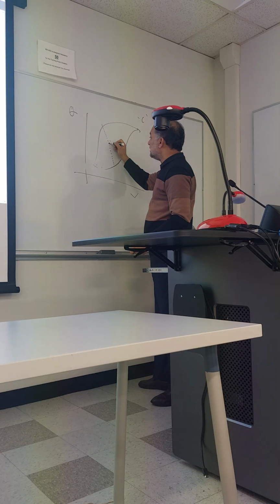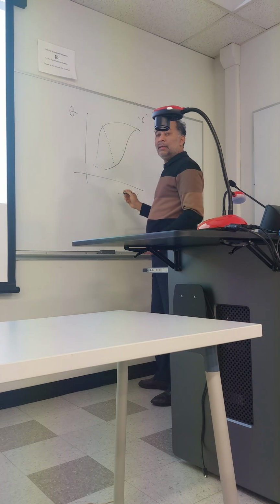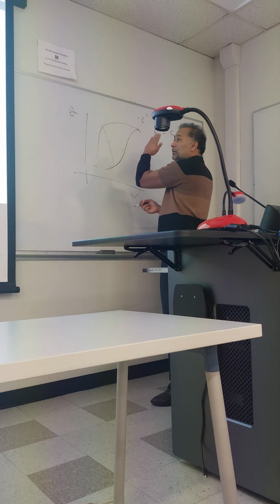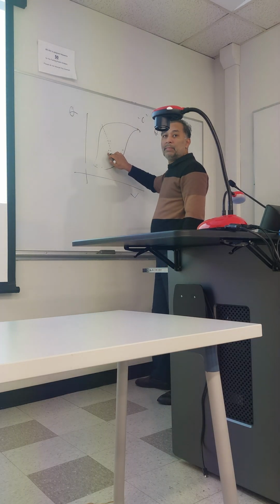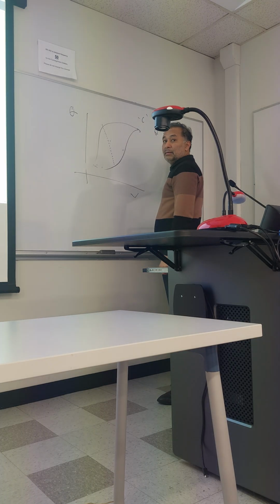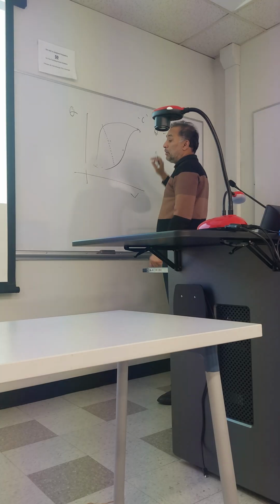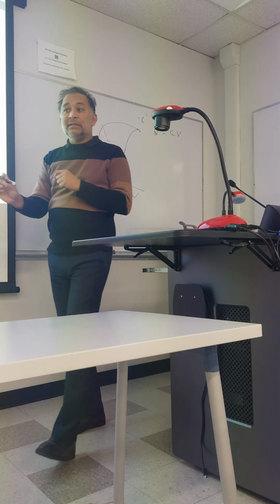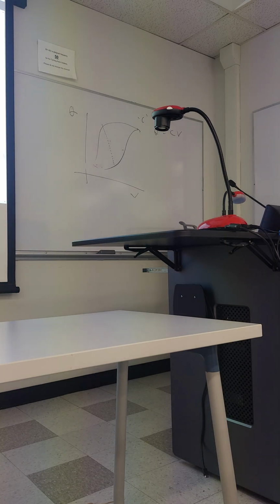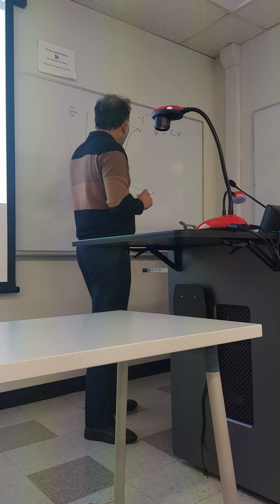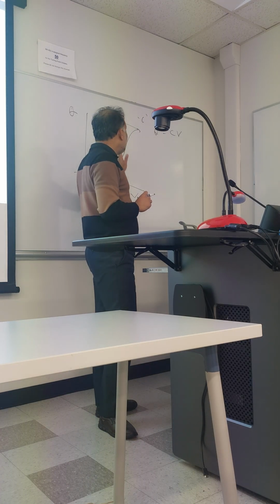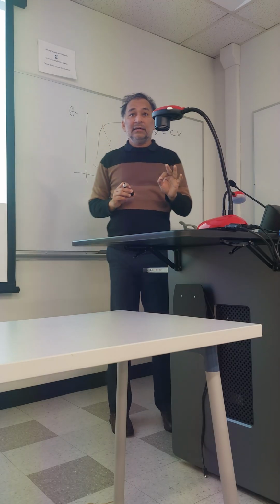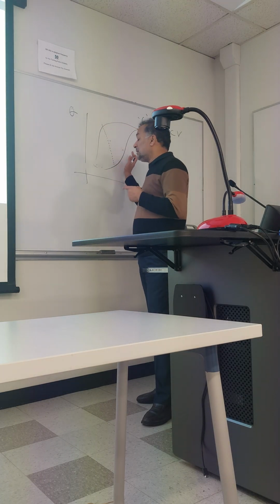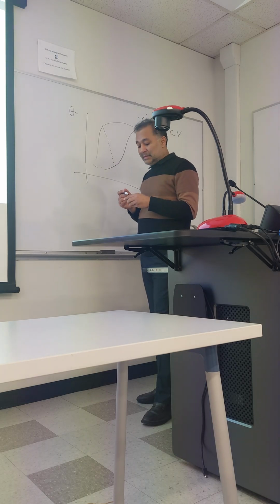This is showing the capacitance, the ratio of charge to voltage. That means instead of this type of curve, it will have a slightly different shape, and this is a negative slope. That means the capacitance will be negative. That means for decreasing voltage, your charge will increase. For increasing voltage, charge will decrease. That way, it gives a concept called negative capacitance. But achieving this condition in the ferroelectric material's behavior is very, very difficult. It is extremely time sensitive, temperature sensitive, and depends on many specific material factors.